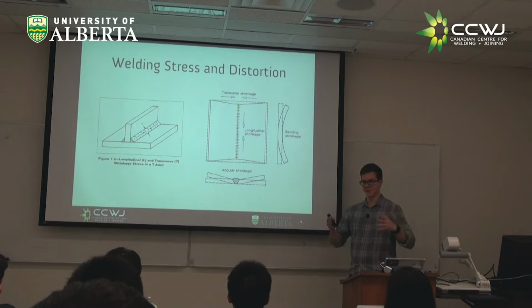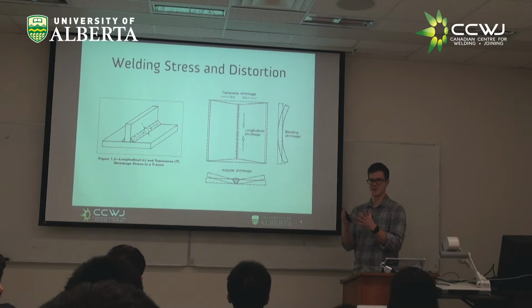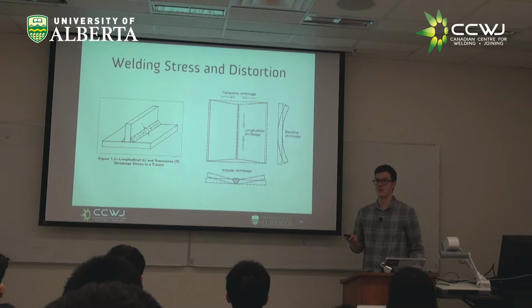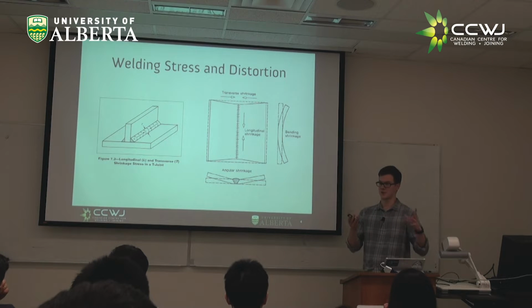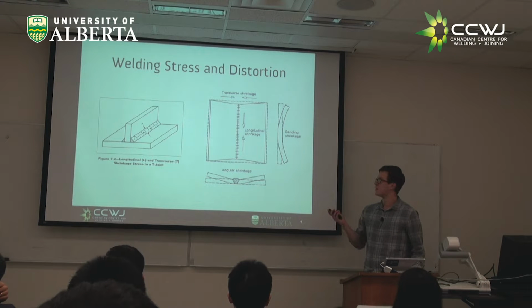But what they're suggesting is if you have residual stresses in an object, typically it's because your object is extremely highly constrained, like we talked about. If you want to heat it and it can't expand, then you develop stresses from that restricted expansion. Same thing with that drop. As the outside is cooler than the inside, when it wants to shrink, it can't because the outside is holding it, so you end up with stresses that develop because of that. Now, if you have something that's not completely constrained, it's free to move, typically then you have different parts that are expanding and contracting at different rates. Parts get locked in during welding where they end up being solid, parts still expand after, and you end up with distortion. Now, in this case, we're going to talk about welding stress and distortion at the same time.